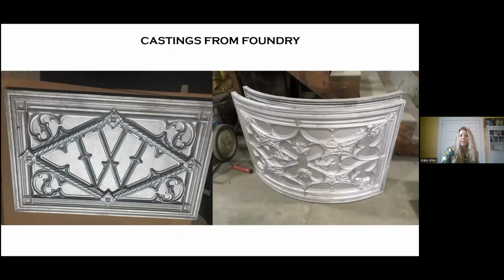And so here are some of the castings out of the foundry, and they've got that Zip-Slip paint still on them, that non-binding release agent. I was really pleased with these, but those curved castings were so difficult to pour. We poured them almost 3 times because you have to have the proper venting, and they also have to be hot enough to push that molten metal all the way through that curve.